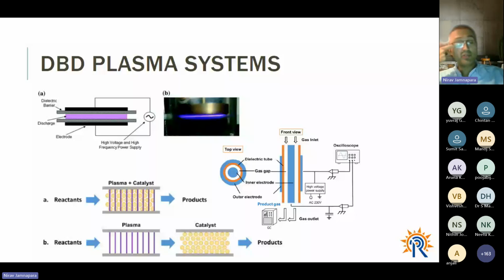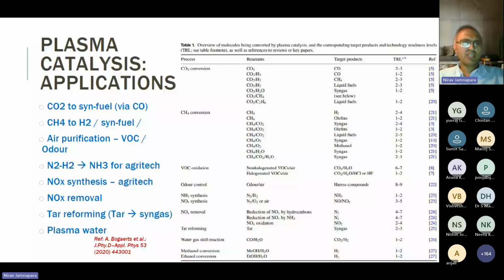The type of plasma used here is DBD plasma, which involves a dielectric barrier discharge layer, and between these two electrodes, the gas is ionized, and there is a plasma catalyst. There are several configurations where plasma and catalyst are either sequential or they are coexistential, and they can work in parallel or in series. And therefore, the reactions, as you can see from this table, which was reported recently in 2020, there are several applications where CO2 to synthetic fuel via CO is referred.